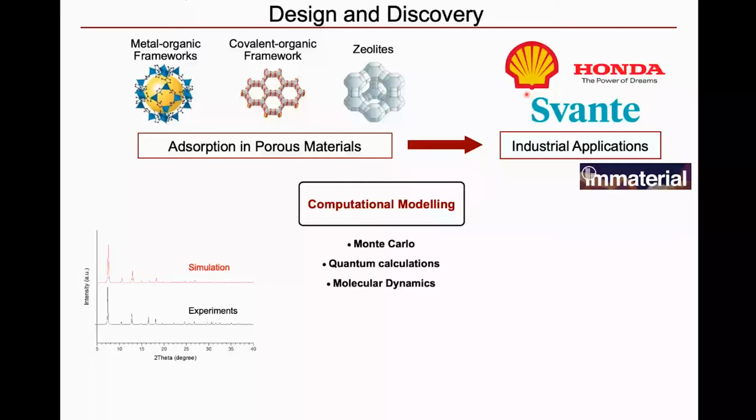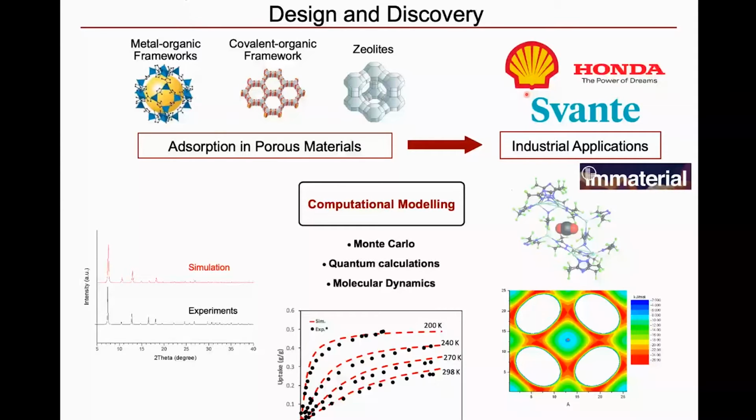We also study adsorption and diffusion properties of gases in MOFs using different computational techniques, including GCMC simulations of adsorption, if you're interested in calculating the amount of gas adsorbed, heat of adsorption, density maps identifying those energetically favorable adsorption sites, adsorption selectivity, if you're dealing with, for example, multi-component mixtures.